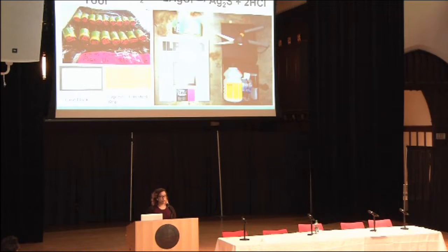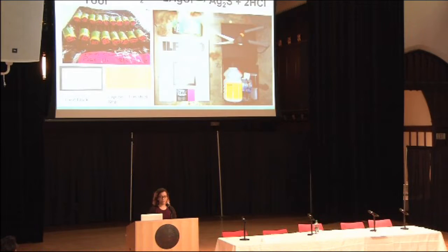And we create the tool using photo paper, photo flo, and glycerin, and make the strips, cut them, place them into film canisters, and set them out for 1 to 3 weeks. Then we fix the paper in a dark room and map them. These tools are designed to be low cost at $1 per canister or less, and the procedures and materials are readily available as research notes on the DIY environmental science site publiclab.org.